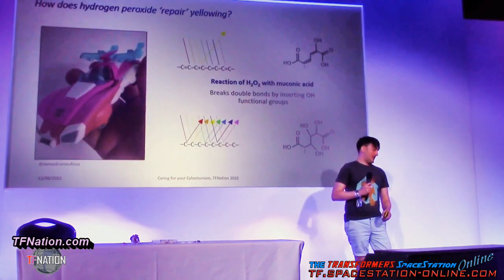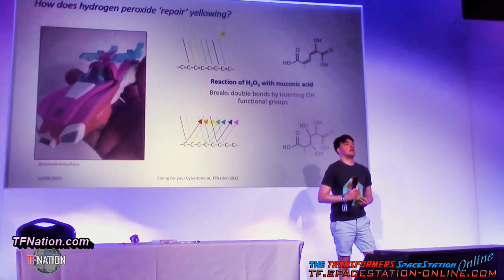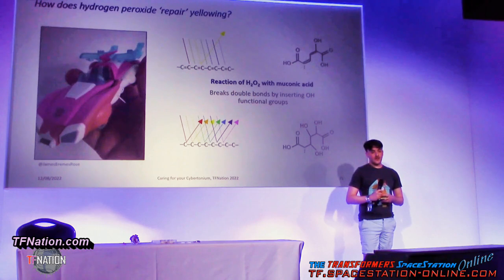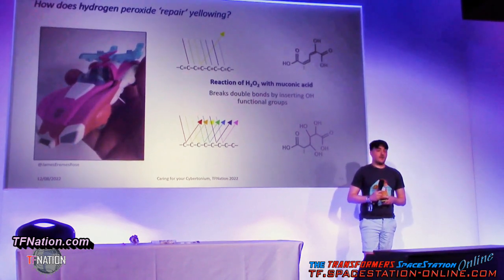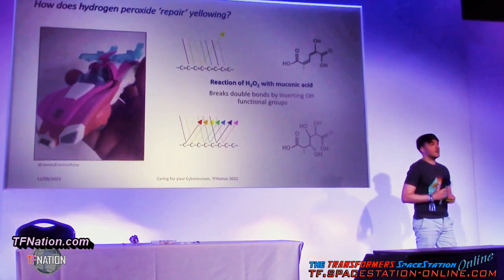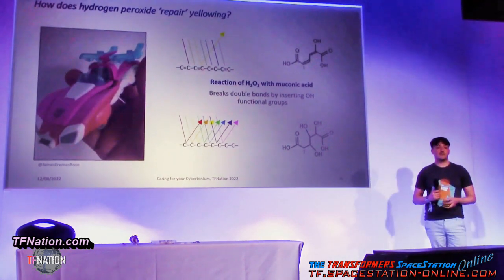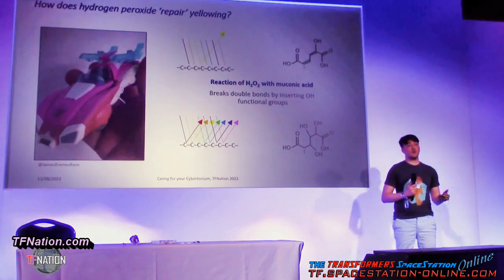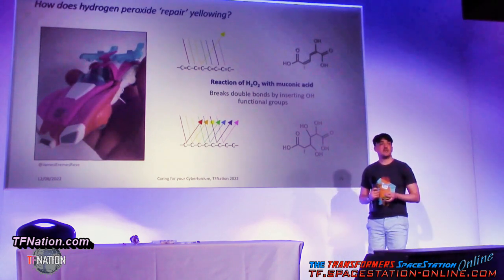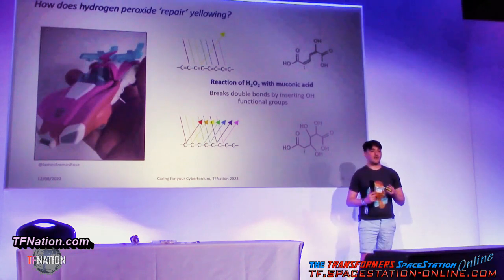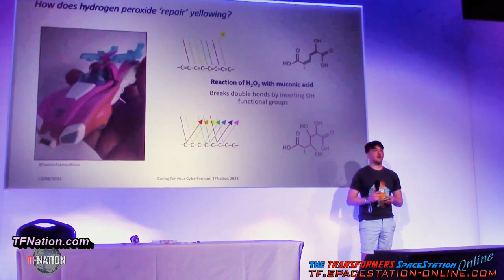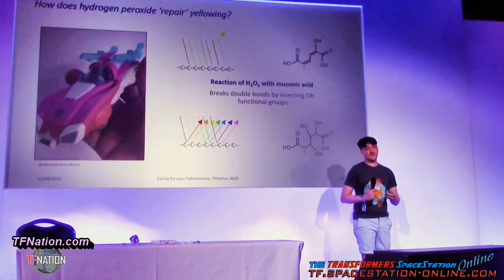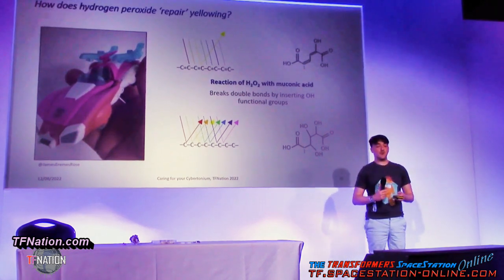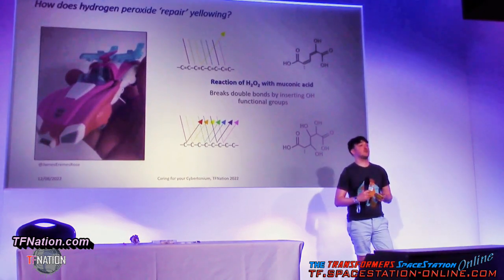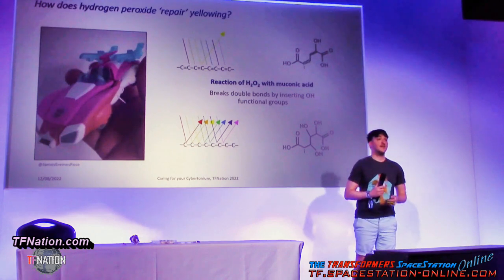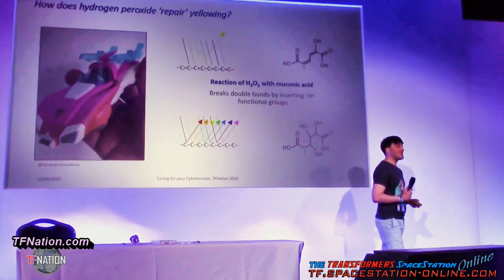Right, so quickly, how does hydrogen peroxide repair yellowing? So a tiny bit of chemistry. It's important here to remember that actually this doesn't reverse the damage. It is a repair. So it doesn't reform the ABS exactly how it was. How it works is that it provides an oxidizing agent. Hydrogen peroxide, H2O2, has all the good things of that. It's got the oxygen, it's got the hydrogen. So by the same means, you put your part in an amount of liquid hydrogen peroxide, and very counterintuitively, you put it back in the sun.